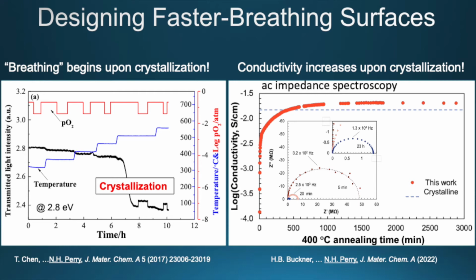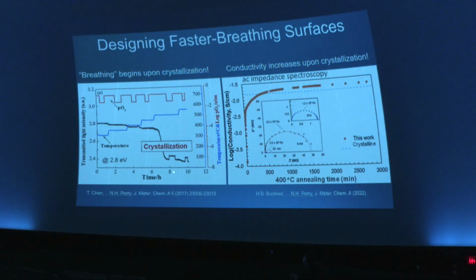So one thing that we started to do was actually monitor the performance of the materials in pretty extreme high temperature conditions as we were making them undergo that transformation from the boring uniform films into these exciting nanostructures. One thing that we found was that they start to breathe when they start to transform and go from that amorphous, glassy state into those crystalline nanostructures. So this is the light that we shine through the sample. This is the temperature. These are the steps of the oxygen. So it doesn't respond to those steps until it transforms, and then it responds really quickly. So that's kind of cool. There's something special going on in the material that changes it from being inactive to active.